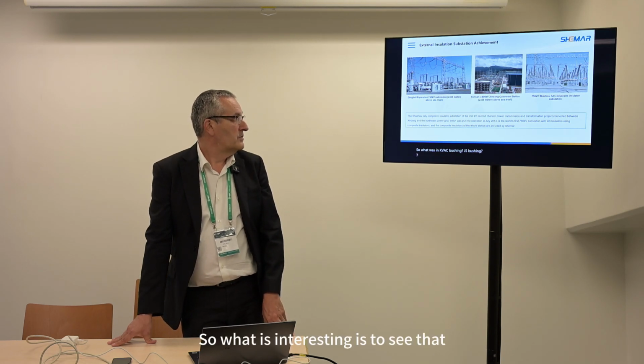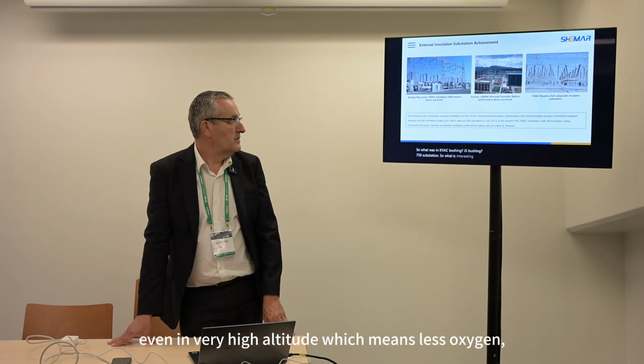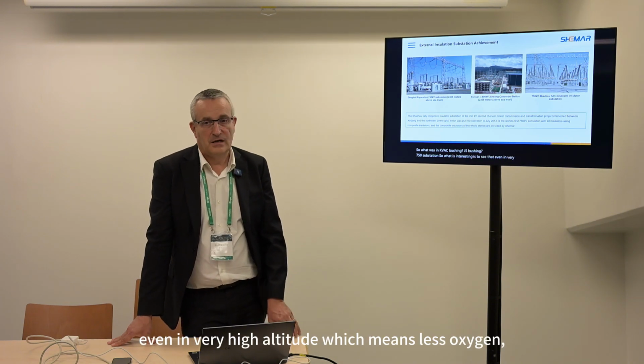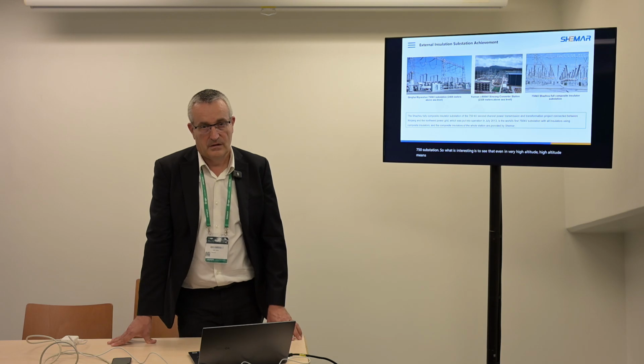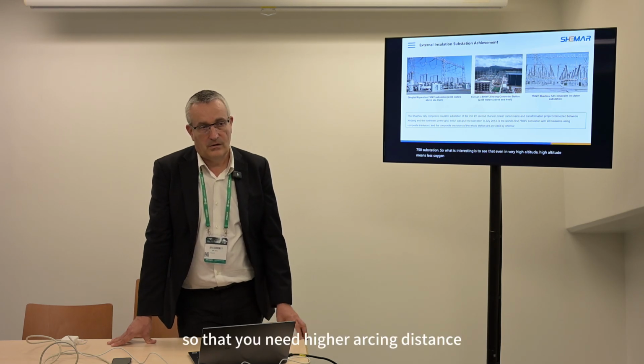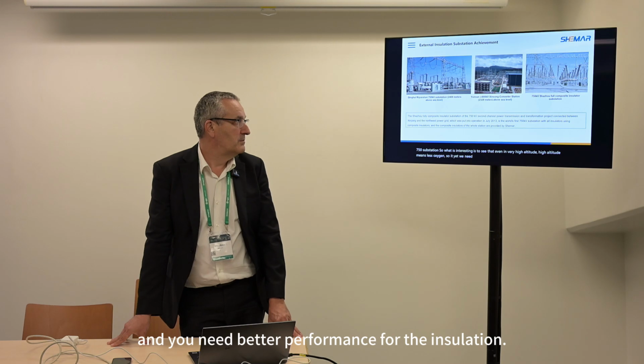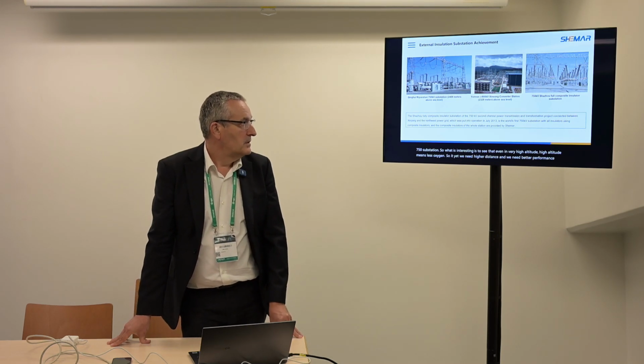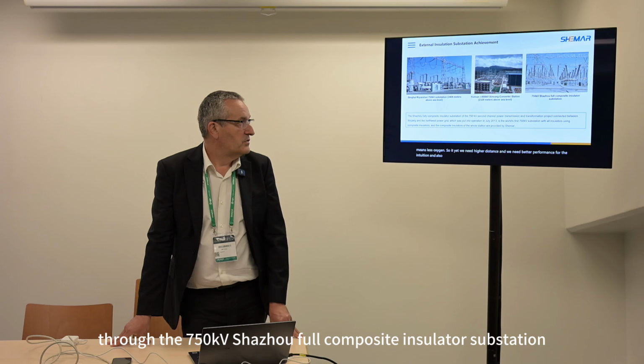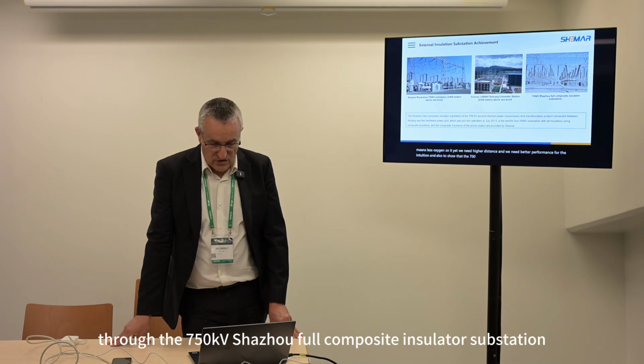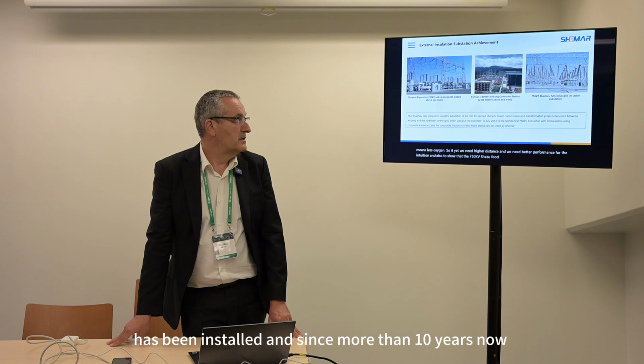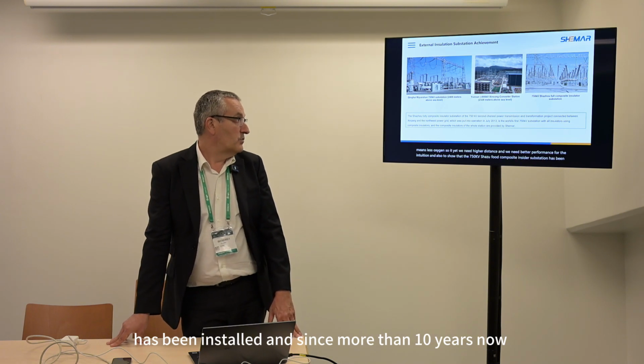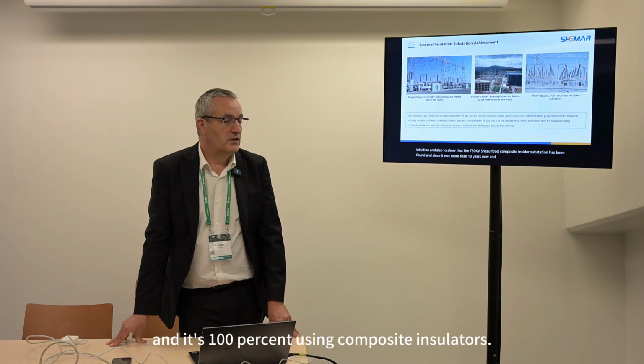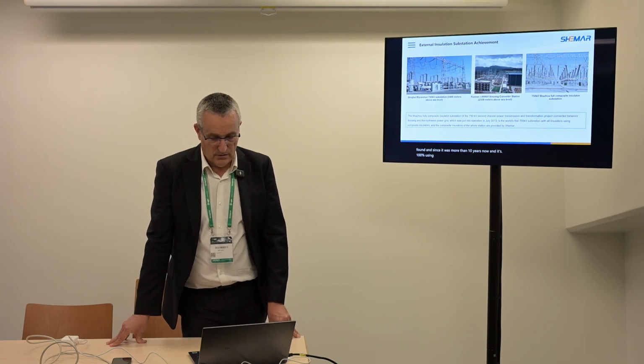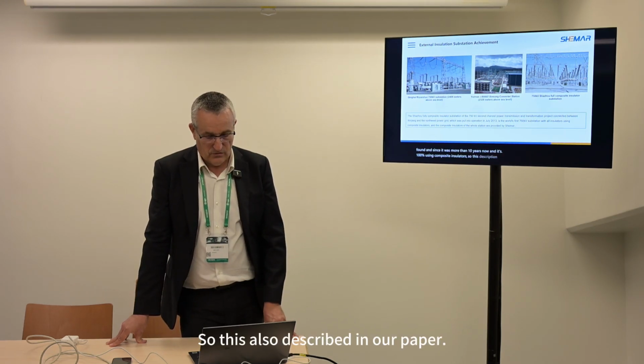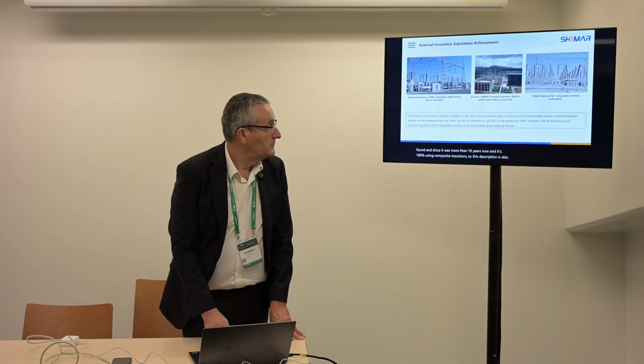750 kV substations. What is interesting is to see that even at very high altitude, which means less oxygen, you need a higher arcing distance and better performance for the insulation. Also, the 750 kV Shazhou full composite insulator substation has been installed for more than 10 years now, and it's 100% using composite insulators. This is also described in our paper.